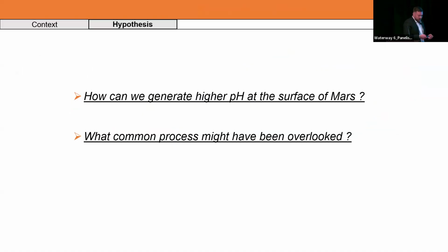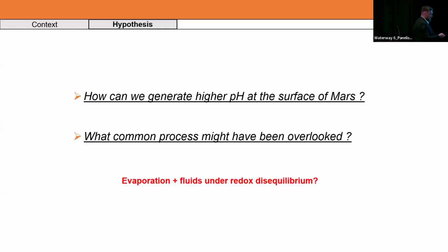And so my idea was that, from the observation that the issue is more the surface pH than the partial pressure of oxygen, we would need at the surface of Mars a new mechanism to explain a rise in pH. And to combine that with the high mobility of iron and manganese, I wanted to explore what happens when you evaporate a fluid and you consider an initial redox disequilibrium.